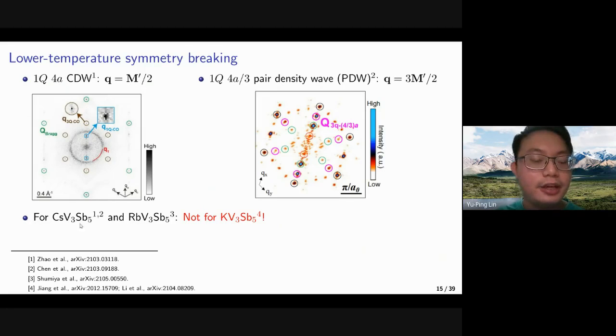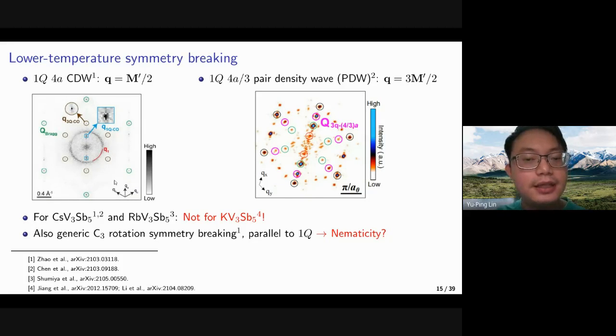And these results were observed only for the cesium and the rubidium, but not for the potassium. Also, in addition to these density waves, they found that there is a generic C3 rotation symmetry breaking, and the direction is parallel to the 1Q direction. This means that there might be some kind of nematicity.